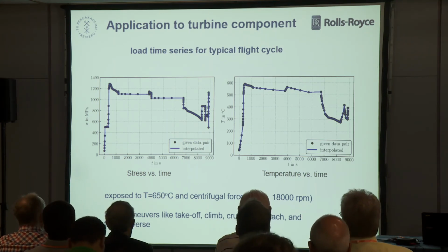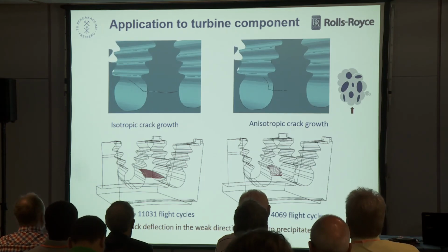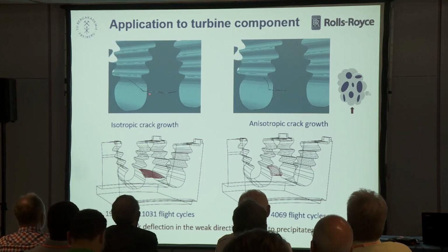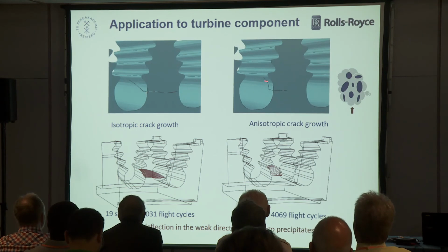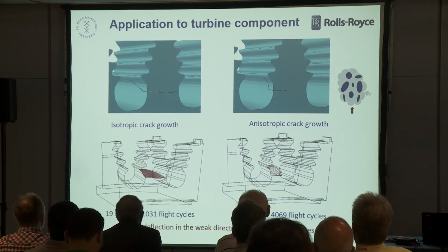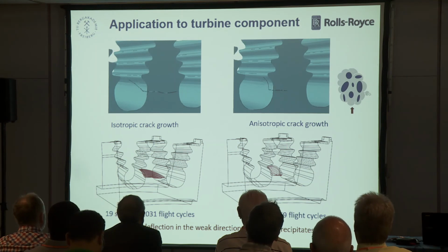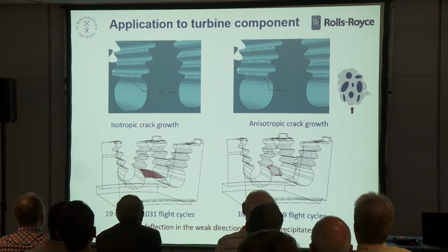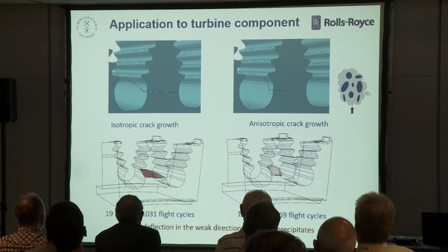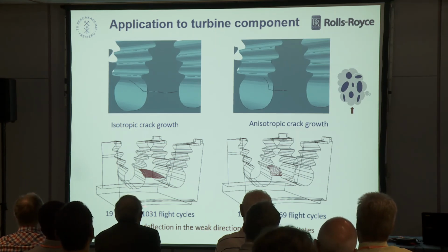So here you see the results. These are the initial corner cracks. Left hand is for isotropic crack growth assumption, and the right one is for the new anisotropic. And here you see the evolution of cracks. And here you see it in this transparent view, you see it better. Each line here is a crack increment step in the numerics. Here we needed 19, and this corresponds to about 1031 flight cycles.